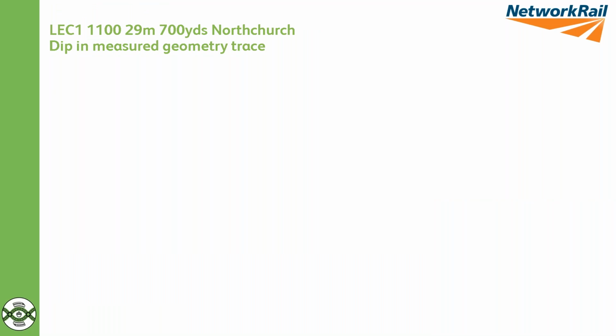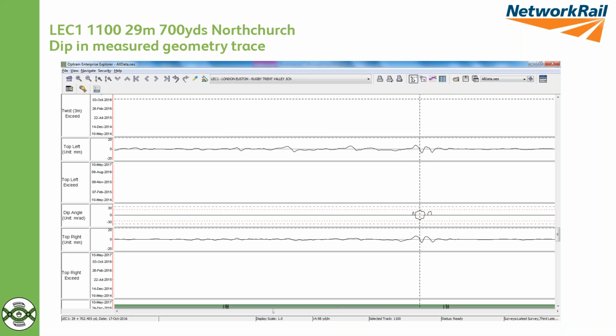Are there other things? And this is a geometry trace from the same break, the previous slide. The only thing, a real note there, it's a pretty good bit of track, good track quality, nice straight track, except for a dip angle. Now, if that dip angle had been an IRJ, perhaps expected, the joint is a little bit softer, but this isn't. This is a bit of plain line and quite a sizable dip angle there for a piece of plain line, and perhaps a clue there that this is a problem location, and where that coincides with older rail, it's been there a long time, then we have a higher risk of foot failures.